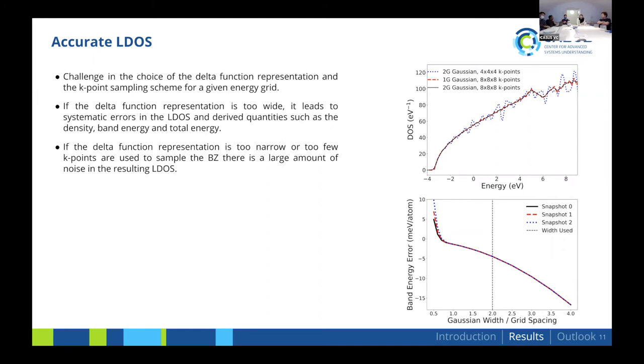Okay. So is there a motivation for using more accurate functionals than you would normally use, because then in that subsequent step there's no... You could do that, if you're willing to spend enough time on training. Basically you would like to have the most accurate training data you can afford, and then train your machine learning model on that. And that's another way of building finite temperature dependence, because here you're using PBEsol, which would not give much difference from PBE, for example. But if you use a hybrid, I think that might give a different answer. Yeah, absolutely. You can increase the accuracy of your model by generating more accurate training data. That for sure is true.